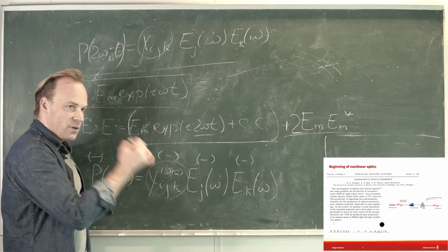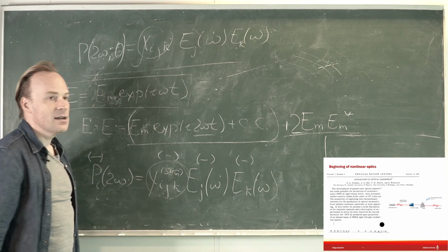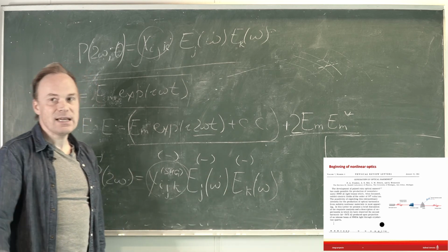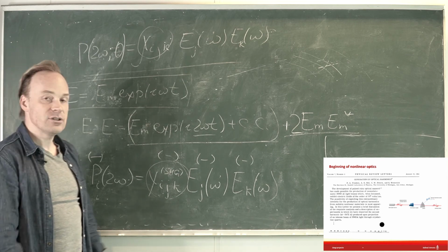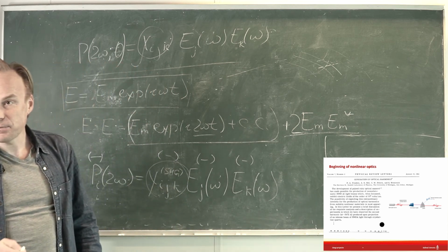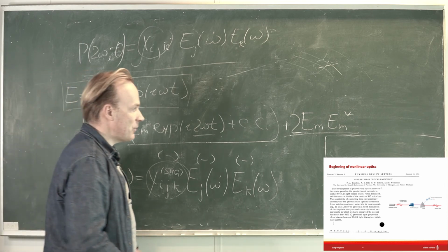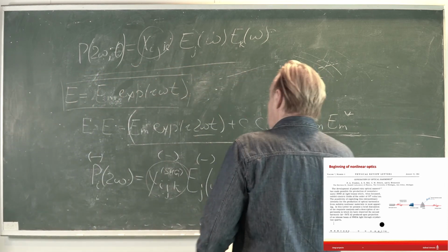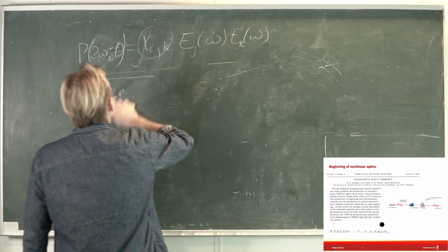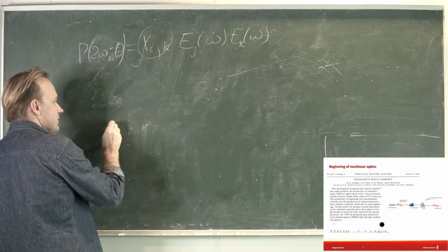It is a polar tensor of odd rank, and the properties which are described by this tensor are only non-zero in non-centrally symmetric media. So basically, if you want to observe second harmonic generation, you should take a non-centrally symmetric medium, exactly as it was done in that paper. You can see here a nonlinear crystal was put in the experimental setup to observe second harmonic generation. But also, second harmonic generation can be observed from centrosymmetric media, in particular from interfaces of centrosymmetric media.